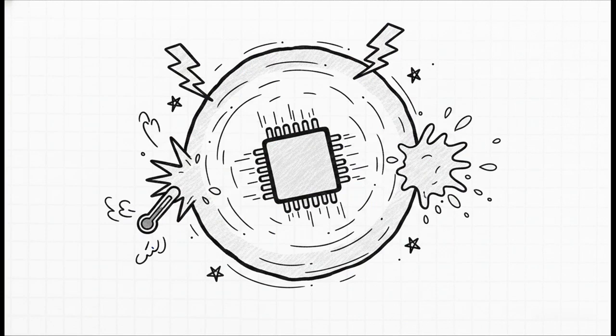First up is physical and chemical passivation. Basically, this prevents environmental contamination from completely ruining the highly delicate circuitry underneath. It is incredibly stable, holding its integrity down to a vacuum of 10 to the negative 9th torr, and it easily shrugs off temperatures past 900 degrees Celsius.